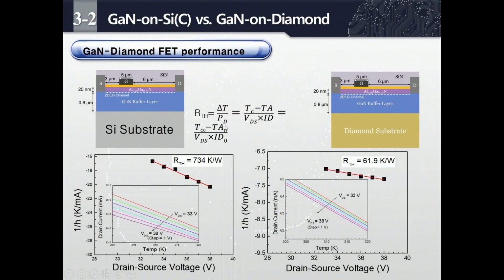So we extracted the thermal resistance by increasing the chuck temperature and measuring the drain current and power. With these graphs, we can extract the thermal resistance. GaN on silicon is 10 times higher compared to the GaN on diamond thermal resistance. So this is the reason for the very strong self-heating effect and also the lower drain current levels.